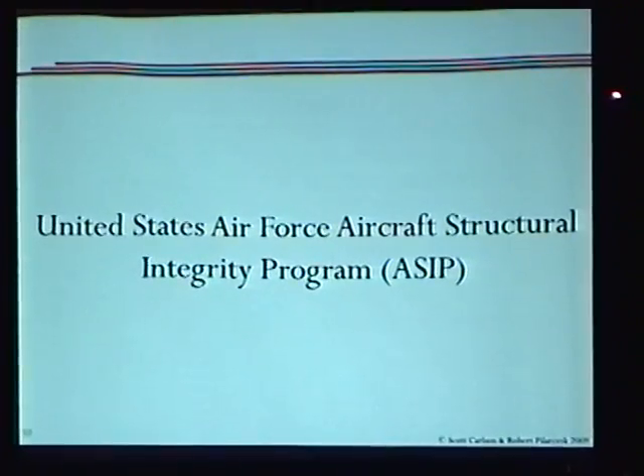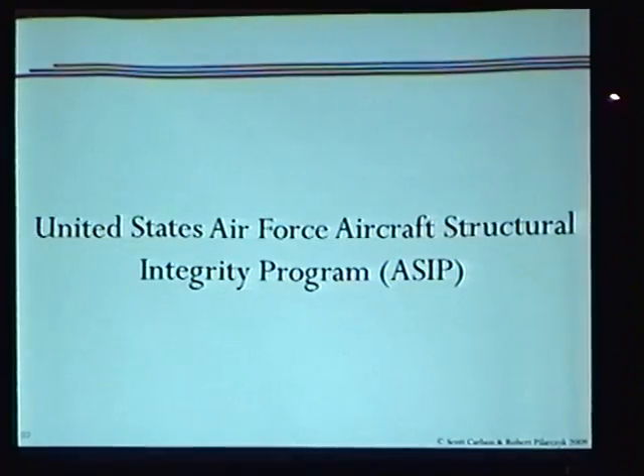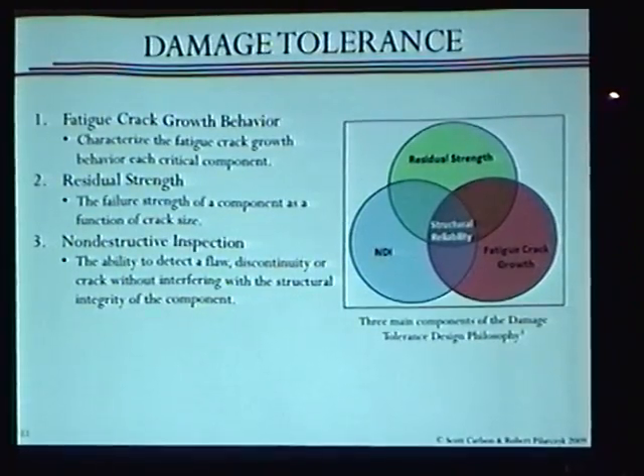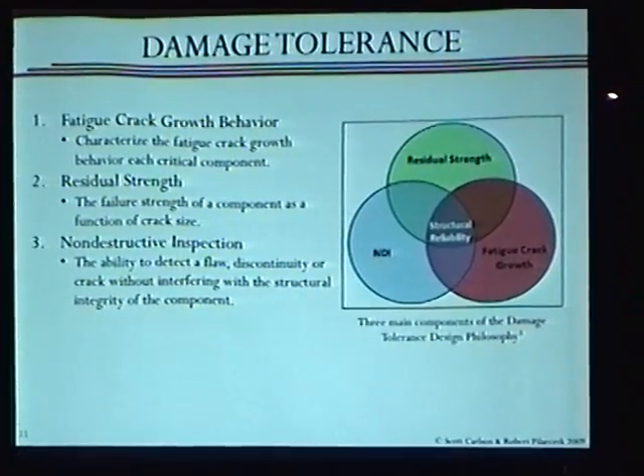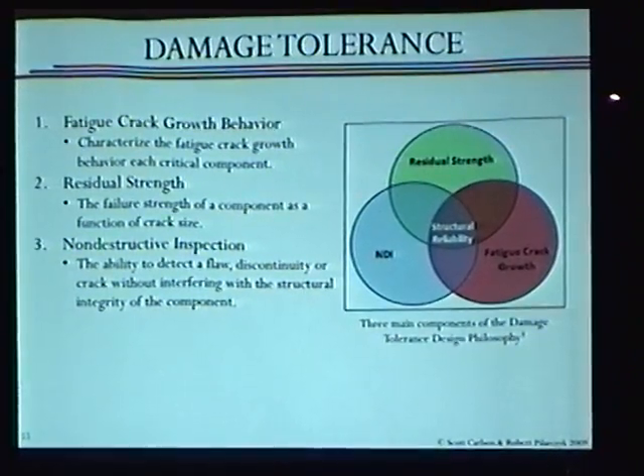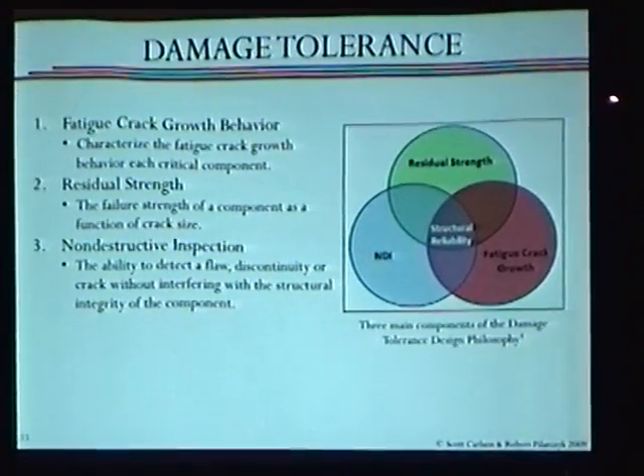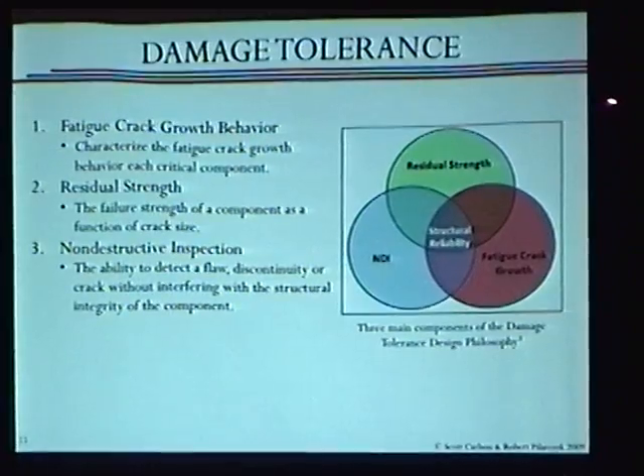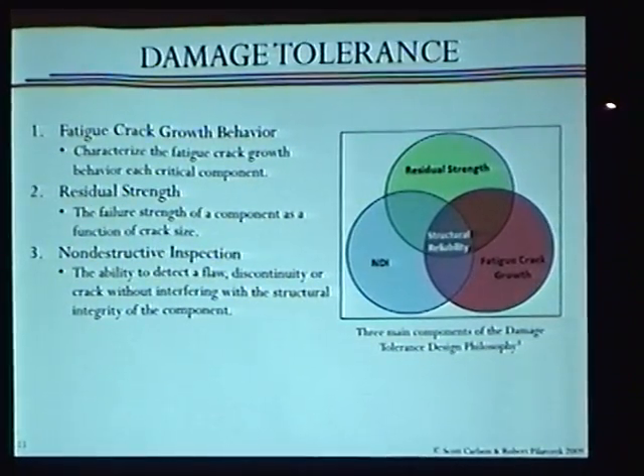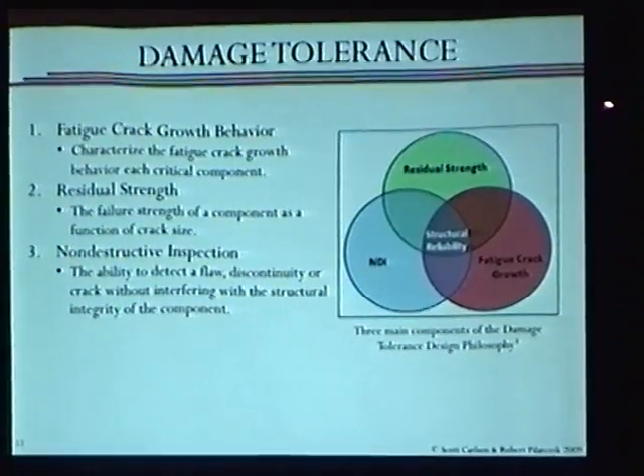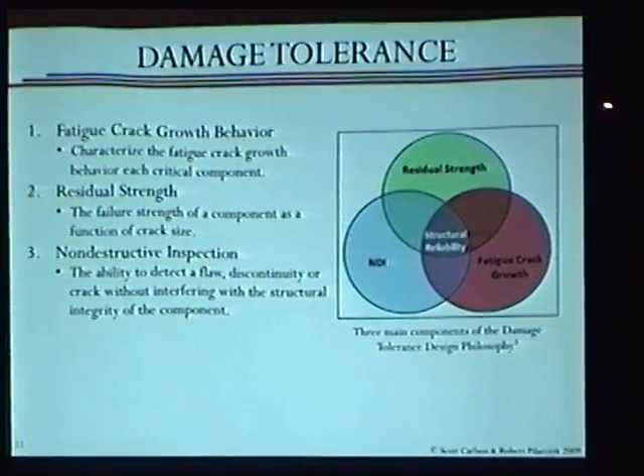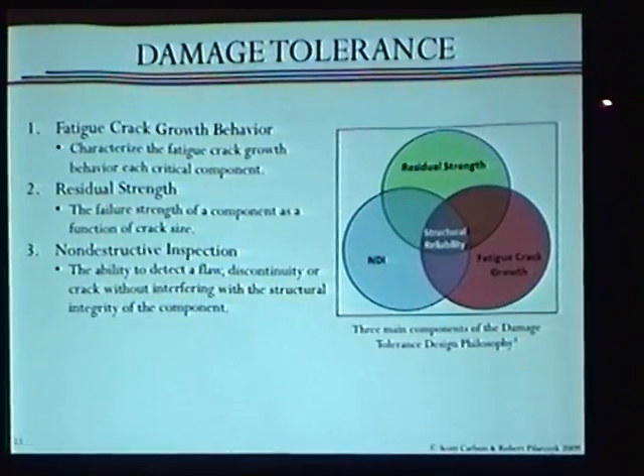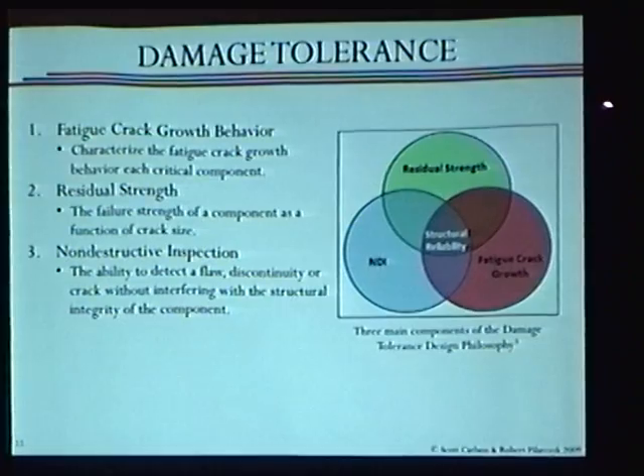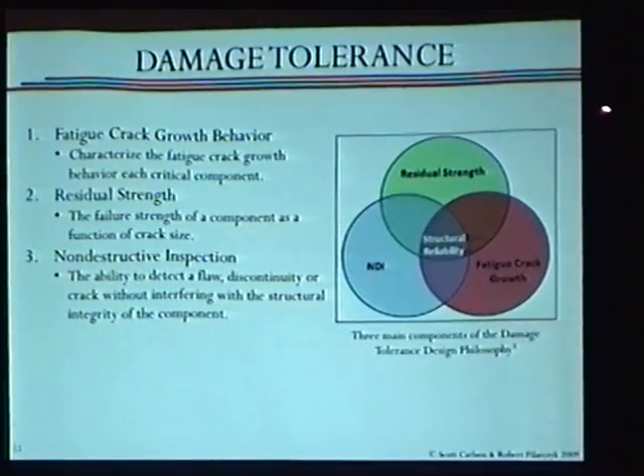So the United States Air Force's Structural Integrity Program. Damage tolerance, which we use to manage our fleets of aircraft, is broken into 3 main sections. It's broken into fatigue crack growth analysis, then residual strength, which means if we have a crack that's this big and we hit this load, what's it going to do? So we need to calculate that. And then the final pillar of this is non-destructive inspection.